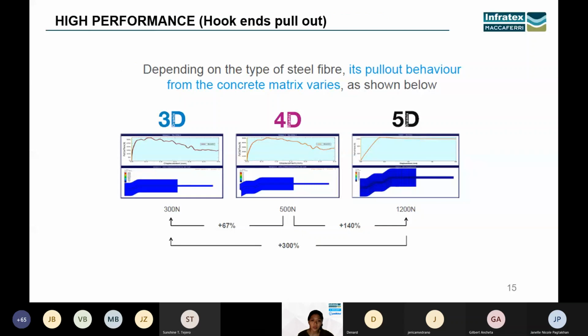So for each type of steel fiber, its pull-out behavior from the concrete mix varies. So as seen on the graph, for 4D and 3D, it shows a similar slip pattern, but for the 4D, it has a slip pattern at a substantially higher level. So for the 5D, as you can see on the rightmost picture, the maximum force is utilized with no slip.